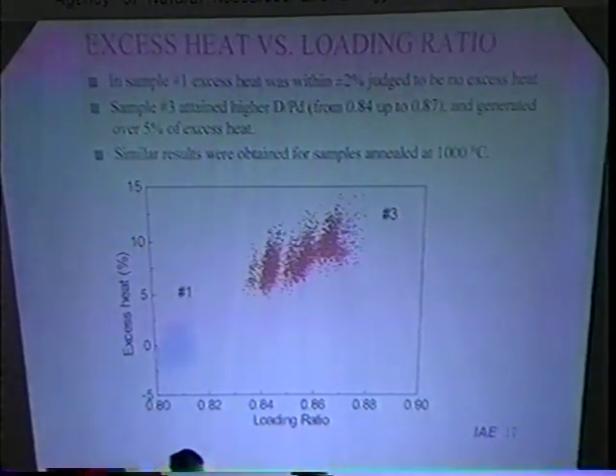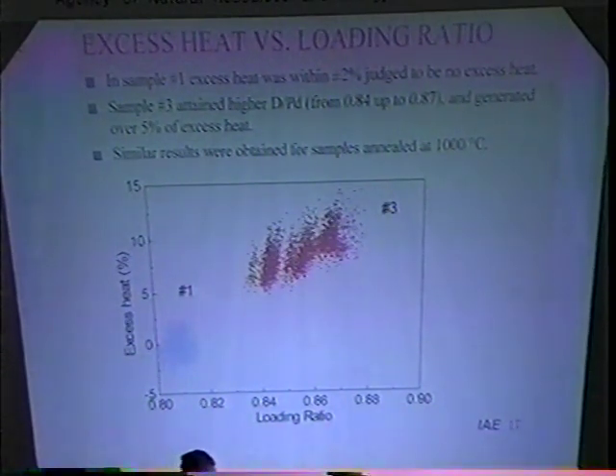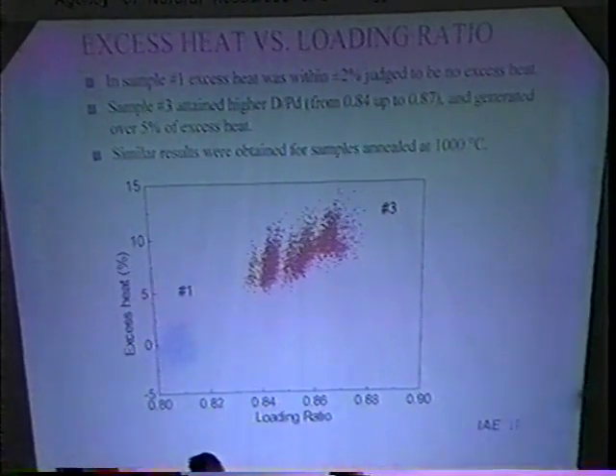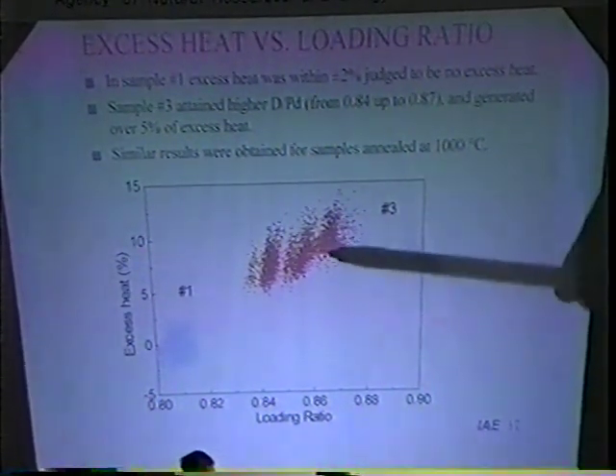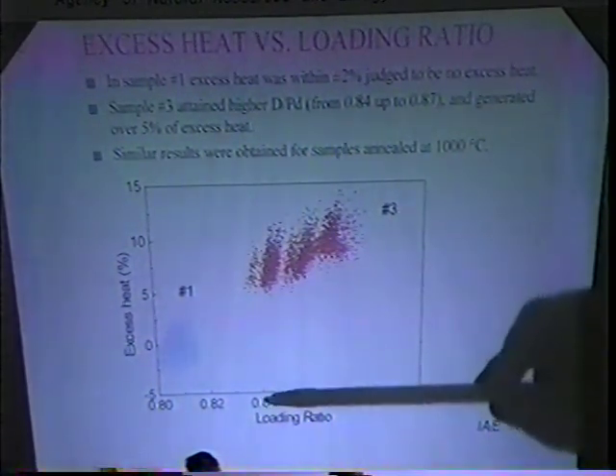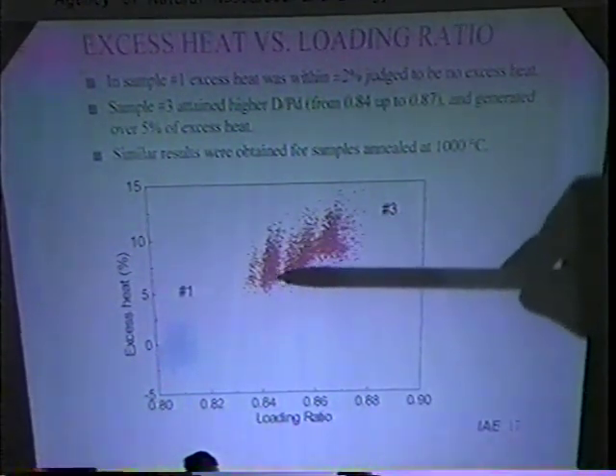And this figure shows the relationship between excess heat and loading ratio. The excess heat of sample number 1 was within ±2%, and we judged it to be no excess heat. Sample number 3 attained higher D/Pd, 0.84 up to 0.87, and generated over 5% of excess heat. Similar results were obtained for samples annealed at 1000 centigrade. Excess heat was only measured for samples annealed for 10 hours. According to these results, the time of 10 hours for annealing was sufficient to recrystallize the grain and to clean the surface by thermal etching. But 1 hour was insufficient in our experiment.